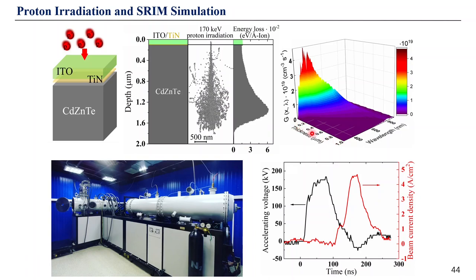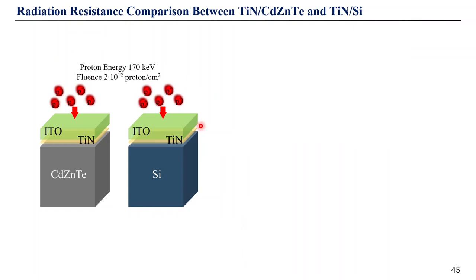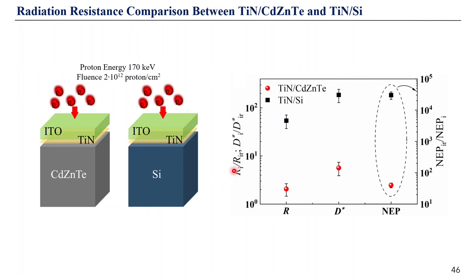most of the photogeneration happens within the first micrometer of the cadmium zinc telluride substrate next to the heterojunction interface. So in this case, we see that we damage the whole photoactive region, and the analysis of radiation resistance is carried out properly. In order to compare the radiation resistance of our device, we prepared a similar heterojunction photodiode based on silicon with quite decent characteristics. And here are the relative changes of key photodiode characteristics before and after irradiation. So we consider here responsivity, detectivity, and noise equivalent power.